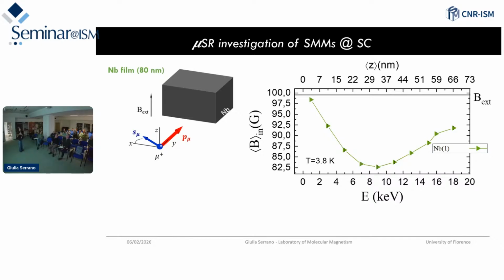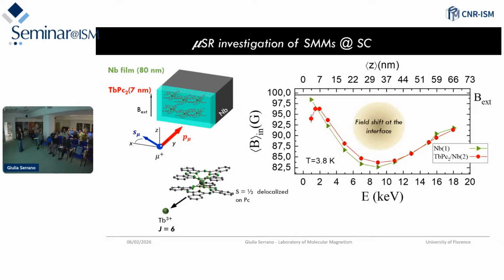What we have done is to use, on top of the niobium film, a 7 nanometer layer of this terbium Pc2 single molecule magnet, which embeds a terbium 3+ ion with a magnetic moment and J=6, and we saw that at the interface we have a sort of proximity effect in which we have an additional screening effect from the external field exerted locally by the molecular layer.